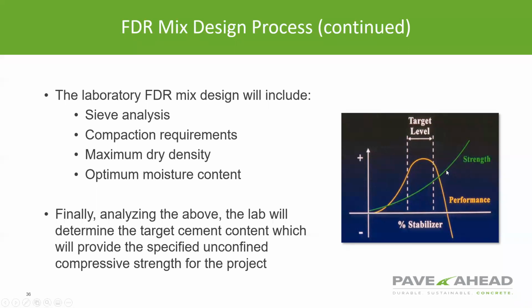However, we don't want to get over in this area where we're gaining too much strength. You know, maybe we're up at 600 or 700 PSI, for instance. If we get into that area, then we may have a problem with drying shrinkage cracking of that base course layer, which can reflect up into the surface layer, the asphalt layer. So we really want a balanced design. We want to be in this area where we have the best performance of our subgrade material and surface course. I guess I would say the best performance of the system itself. At the end of the day, that's what is most important.